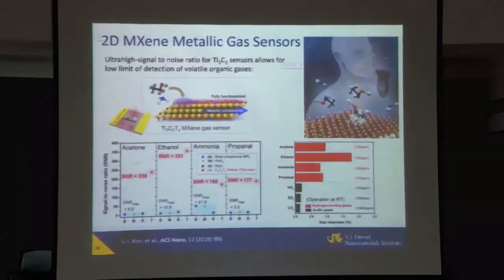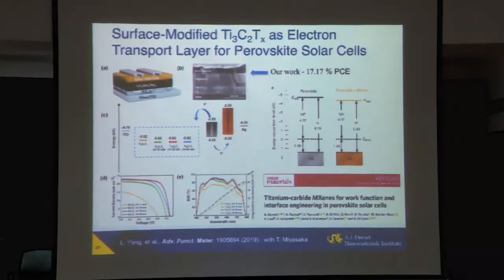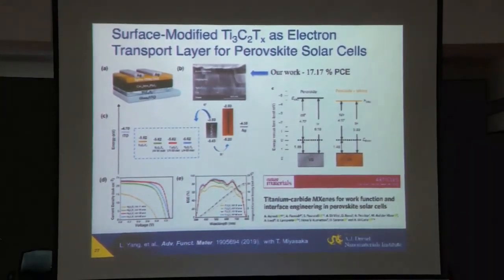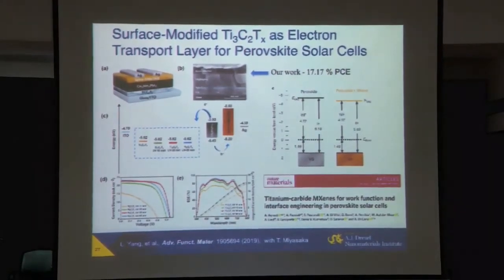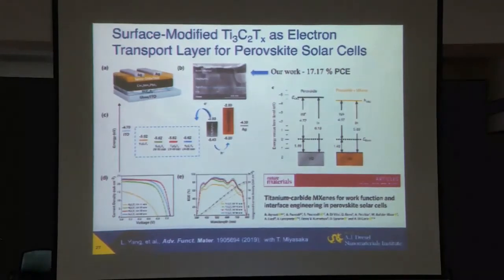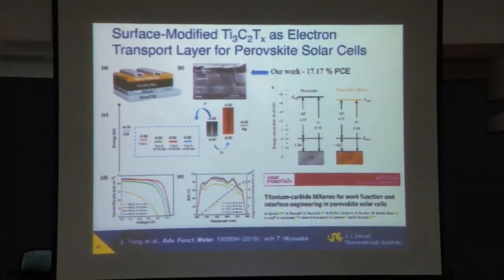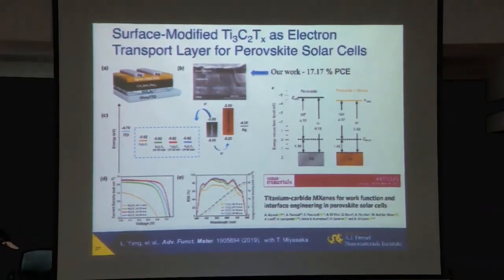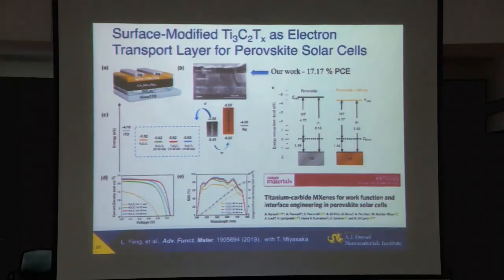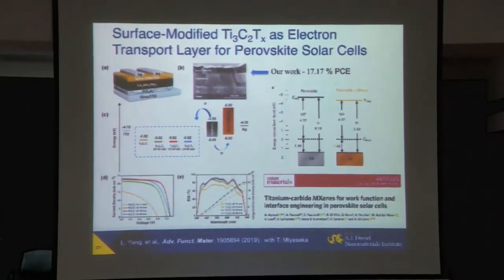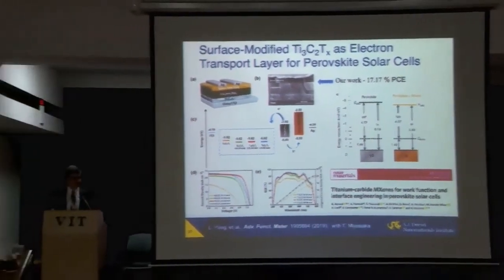But also, of course, you can change it permanently, and this was done in the case of solar cells, basically by changing surface chemistry. OH will actually take it to roughly probably minus 2, but fluorine can drop it down to minus 8. So basically it's a lot. We cannot do it reversibly, at least we don't know how to do it reversibly, fluorine, hydrogen, but oxygen right in the middle, like minus 5. So in this range, it's pretty easy to tune by, for example, drying it, heating it, removing hydrogen from the surface, or we can get more fluorinated material by using HF. So this is a range we can play with. We published a paper in Chemistry of Materials, basically on tuning work function of MXenes earlier this year.